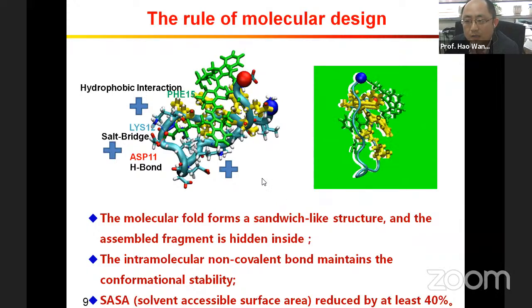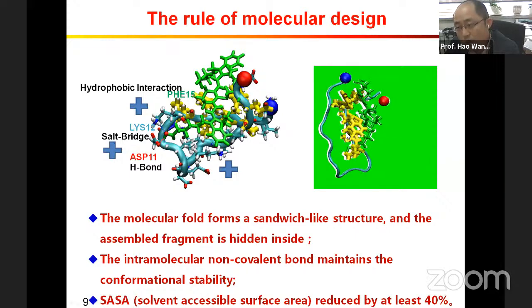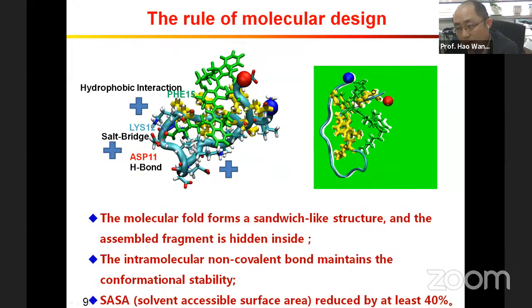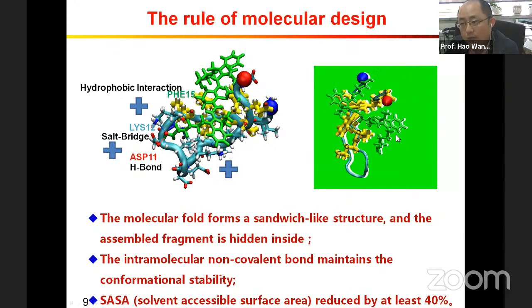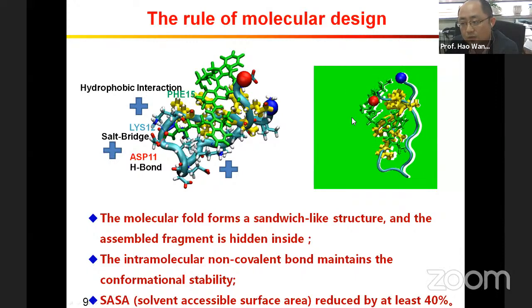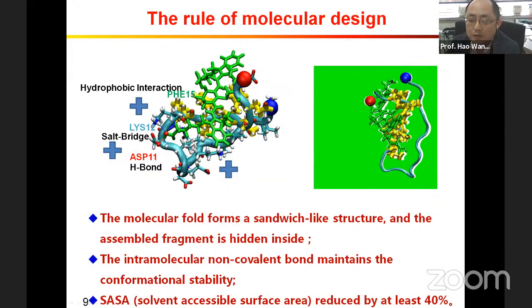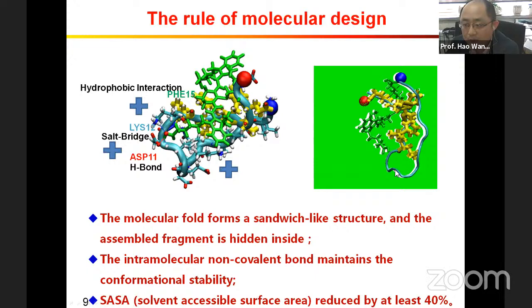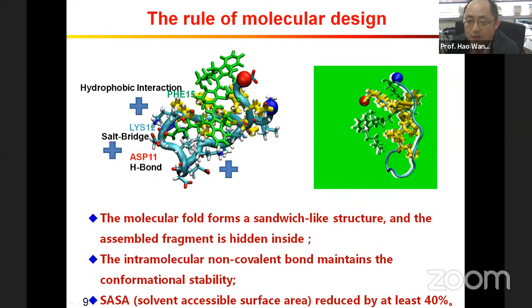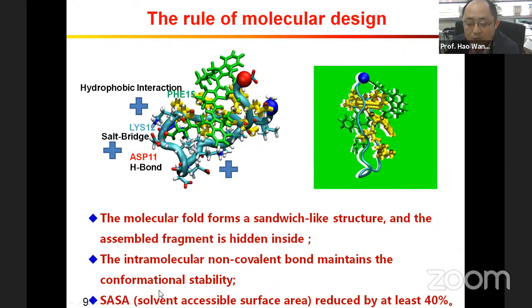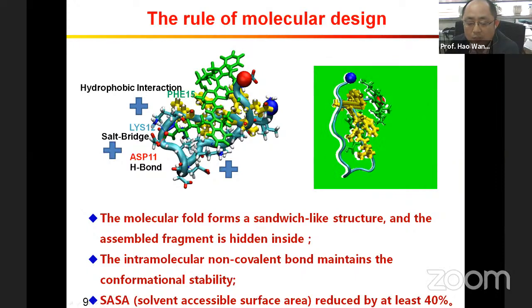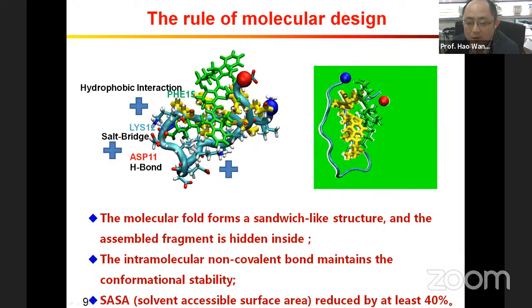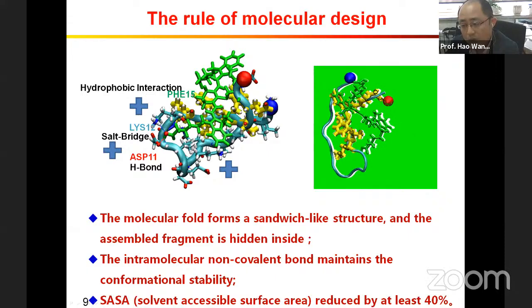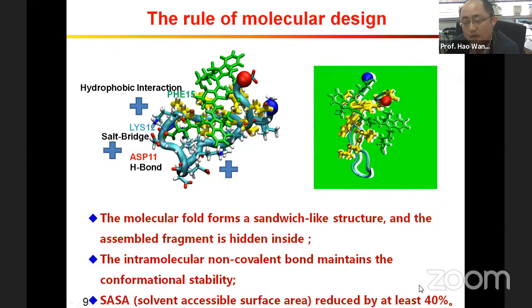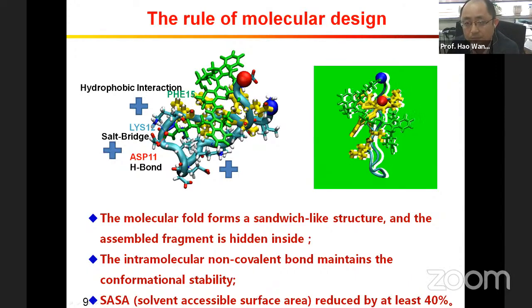And for the molecule design, when we do this full-length molecule, it self-folds into this sandwich structure. In the middle, the yellow part is hydrophobic and a very sticky part. In the beginning, the sticky part is encapsulated inside of this big molecule, and it cannot go bigger and aggregate. When the molecule is cleaved from here, the sticky part is exposed and initiates this aggregation. Based on our simulation, we determined one critical parameter, we call it SASA, the solvent accessible surface area. When this area is reduced by at least 40%, this is a very critical number for the molecule design.